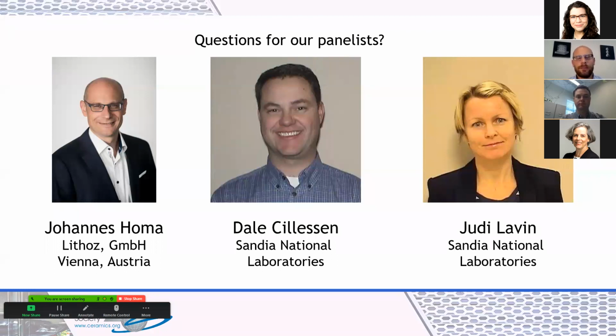Yeah, I think, first of all, to have a general answer to this question, with additive manufacturing we cannot solve material issues which are existing. So you have to match, of course, the powders and adjust the sintering temperature to get the same sintering temperature for the two components. This has to be done, and this is a normal ceramic issue, which has to be also done for additive manufacturing. But I think what's key here is that we can really selectively put ceramic particles or ceramic materials where it is really needed.